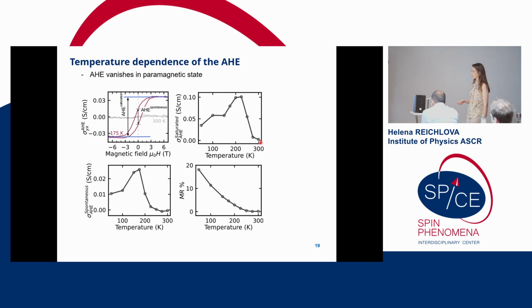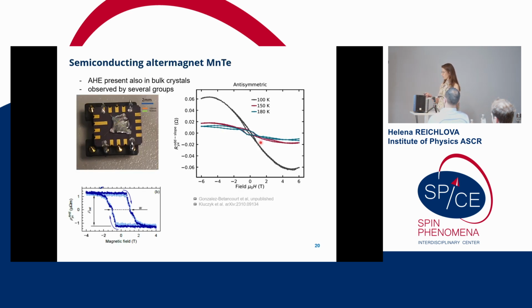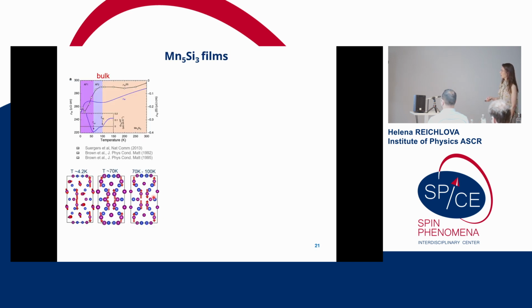This was some time ago, already 2 years ago, and since then it was reproduced by a couple of groups, not only in thin films but also including in our group. We can now see this anomalous Hall effect present also in the bulk. You see a very dirty experiment, just putting 4 wires into a piece of manganese telluride, and we can observe the anomalous Hall effect there. Again, a few other groups already confirmed that this is present there. So this is manganese telluride. It's a nice thing. And then another candidate which I will talk about is Mn5Si3.